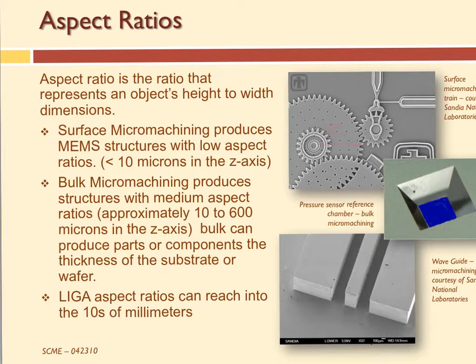So surface micromachining is pretty low aspect ratio. LIGA aspect ratios can be as high as 10 millimeters tall and hundreds of microns wide or tens of microns wide. So you can get very high aspect ratios. In bulk micromachining, you can get fairly high aspect ratios because you're going through the whole wafer. They have something called the Bosch process, deep reactive ion etching, where you can etch very thin structures, very deep channels. You can make a hole right through the wafer, so you can make a 10 micron hole that goes through a 600 micron wafer. Wafers are 600 microns. What's the aspect ratio of that hole? 600 deep, 10 microns in diameter. Yeah, 60 to 1, 100 to 1, on that order.